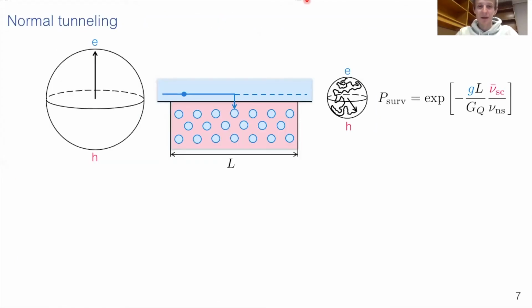We think that the reason for the discrepancy is that actually here we are dealing with a type 2 superconductor that is subjected to a pretty high magnetic field. So this type 2 superconductor is actually in the mixed state. There is a vortex lattice, and the cores of these vortices are just chunks of normal metal. Before, we assumed that the quasi-particle that was incident on the proximitized segment of the edge was transmitted across it with essentially a unit probability. So it always reached the downstream electrode, either as an electron or as a hole.